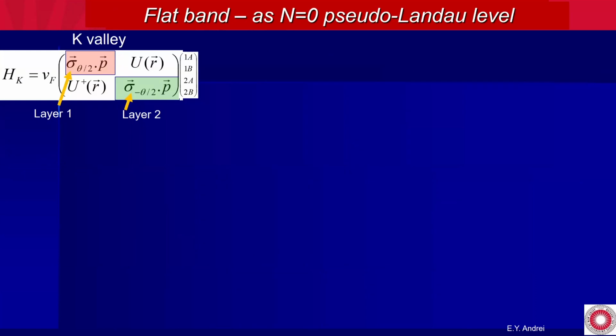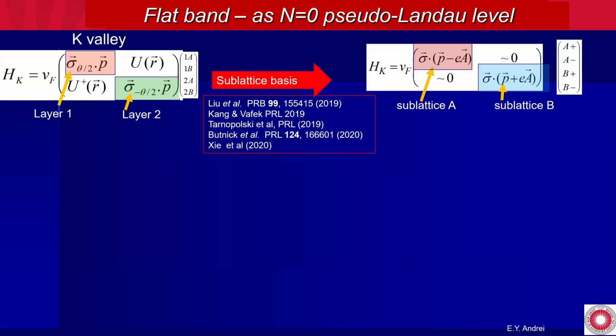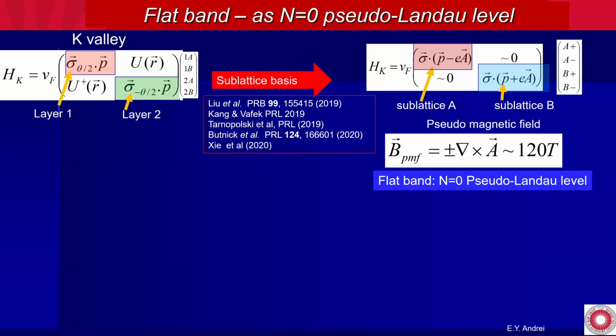Okay, so here is a little bit of theory. If you write down the Hamiltonian in the K-valley here, layer 1 is in pink, layer 2 is in green, and the off-diagonal blocks are the tunneling between the 2 layers. So this looks pretty complicated, but if we do a little change of basis, from the layer basis to the sublattice basis, something very interesting happens. Now you see that in the top layer, this is the A sublattice Hamiltonian. You have a Dirac-Weyl Hamiltonian with a gauge field that has opposite signs in the A and B sublattice. And then you can calculate that this will give you what we call the pseudomagnetic field.